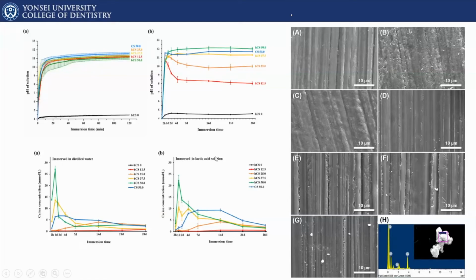Also, both in distilled water and lactic acid solution, they release calcium ions, which is responsible for dentinal tubule occlusion. As you can see here, compared to control, there is more occlusion of dentinal tubules when they have a high level of hydrated calcium silicate. And when we analyze these particles here, they are calcium and silicate-based materials.